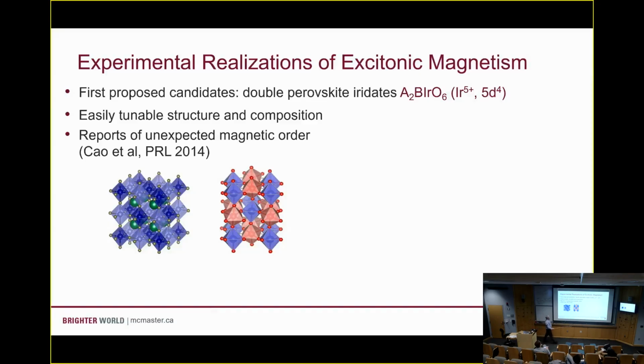So we have this general form A2BIrO6, and there's a host of different elements we can put on the A site and the B site. This gives us a way to tune the moments, the lattice constants, bond angles, if you like. So we have a lot of freedom to play around here with composition. And in a number of these compounds, there are reports of magnetic order. Again, magnetic order in these materials that should, by all accounts, be non-magnetic.